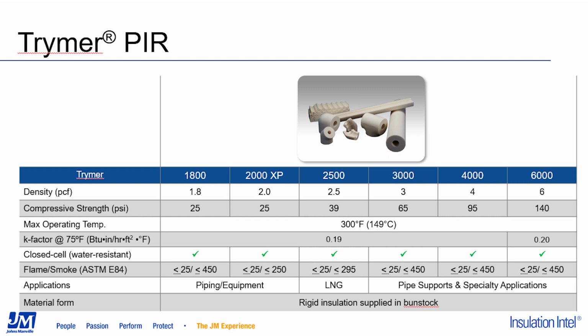This product line is primarily used as pipe, tank, and equipment insulation from cryogenic temperatures up to the 300 degree F maximum exposure temperature for all of this product line. With the exception of the highest density Trymer 6000 product, all of these have the same thermal conductivity performance with a very good value of 0.19 at the standard 75 degree F mean temperature. As you can see, the compressive strength increases as the density is raised, and our highest density Trymer 6000 actually has higher compressive strength than standard cellular glass.